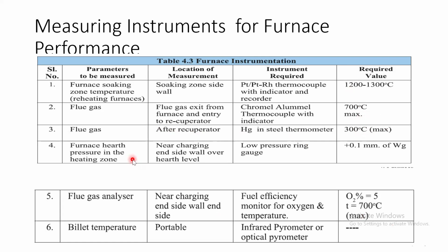Now furnace hearth pressure in the heating zone, near the charging side inside wall over the hearth level. The instrument required is a low pressure ring gauge, meaning a gauge which can measure pressure in a least count of 0.1. The required value is plus 0.1 mm of water gauge. Here they measure the pressure in mm of water gauge. So this furnace hearth pressure is measured near the charging side inside wall over the hearth level. This is how the parameters, location of measurement, and the instrument required are tabulated.